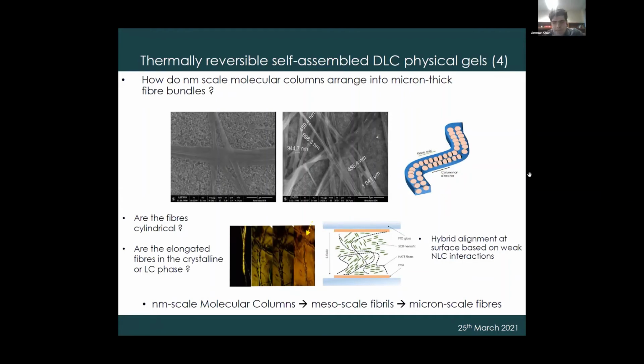Coming back, the next question we wanted to answer was how are these distorted liquid crystalline molecules oriented at the surface of these supramolecular fibers? And to study that, what we did was we actually made these quite interesting cells. So these are sandwich cells where you have these fibers, which are the black dotted lines here, and we filled these cells with a nematic liquid crystal, 5CB, 5-cyanobiphenyl, and we tried to figure out what the alignment of the 5CB is on top of these fibers.